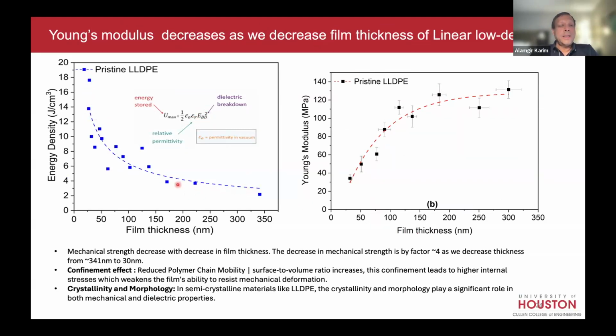It's still 18 divided by 2, about 8, 9, so this is still very attractive. But here you can see that the modulus drops. This is what I was saying: polypropylene is the only polymer where modulus increases as well as energy density increases. All the other polymers, glassy polymer, block polymer, LLDP, anything that is glassy or amorphous with low crystallinity, drops.